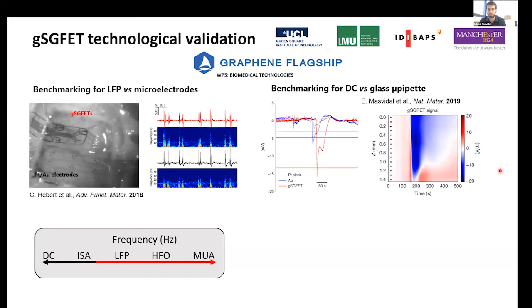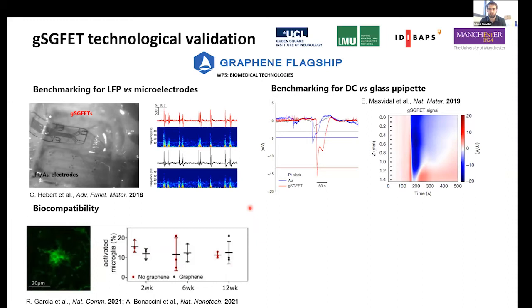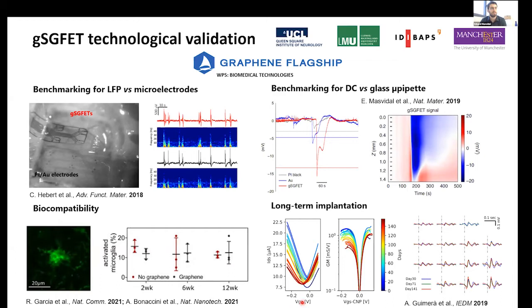We have checked the biocompatibility of these devices and observed no significant microglia activation using graphene. We have also studied the chronic use of this technology. The transfer curve and the transconductance — the coupling of signals in these devices — only slightly reduced during chronic implantation, but this is still enough to observe evoked potentials over the whole duration of the implants.